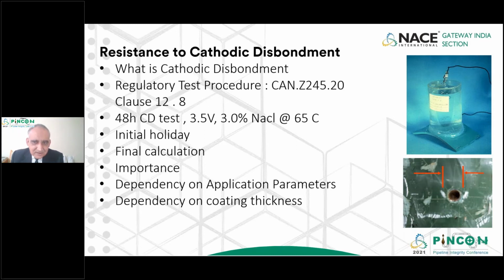3.5 volt DC is applied to the circuit, and the temperature of the assembly is kept at about 65 degrees Celsius, either by using an oven or a sand bath with heater. And this test has to continue for at least 48 hours. This is a highly accelerated condition of the corrosion which happens in service conditions.